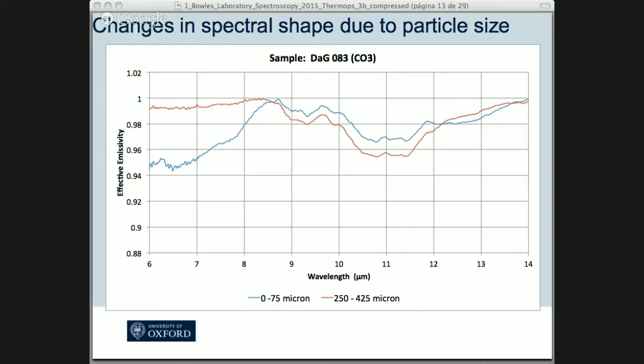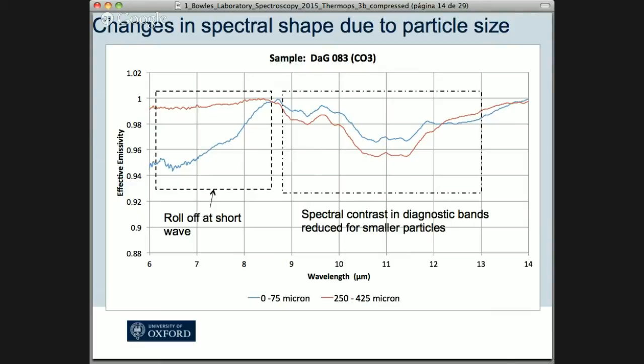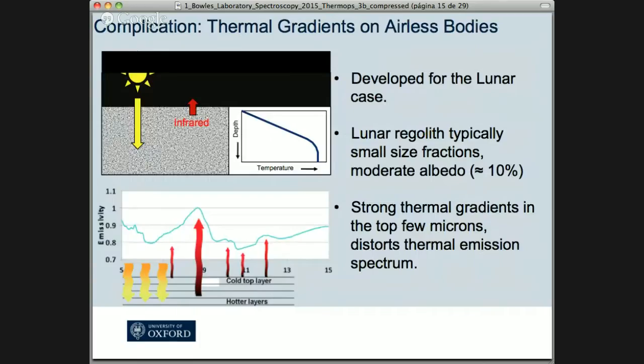The other thing that can happen, of course, is that you've got no air, which is a really interesting effect, because what you end up with is gardened, impact-driven regolith being produced on some of these objects. Certainly on the moon, this is the case. That means radiation now starts to dominate because the thermal conductivity is so low in the way the energy gets transported around in the regolith. And that leads to these extreme thermal gradients. So as Paul mentioned earlier, you can get tens to hundreds of Kelvin temperature difference in the top few microns, few hundred microns or few millimeters of surface depth.